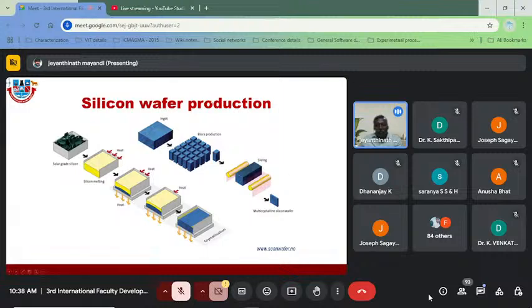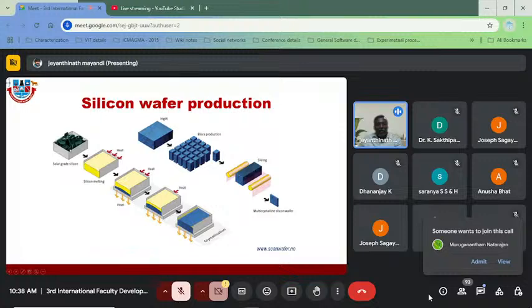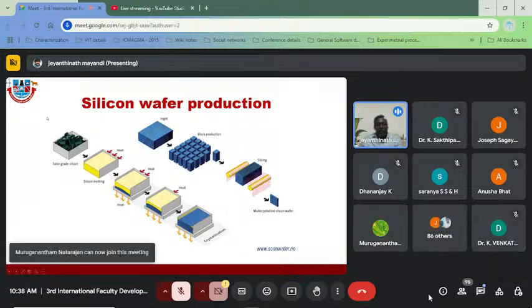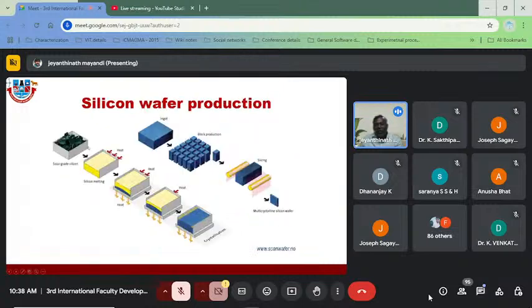And this is how an ingot is made from silicon production. Solar grade silicon, these chunks, are taken and melted. They heat it to very high temperatures, more than 1400 degrees Celsius, in a crucible, and make it liquid. Then they start to crystallize using a small seed crystal, leave it for a while, and they get an ingot. This ingot is sliced into blocks, and the blocks are sliced into wafers. This is taken from Scan Wafer in Norway. There are many different companies in Norway that can produce silicon with different kinds of impurities and levels, and they can also make polysilicon and monosilicon.